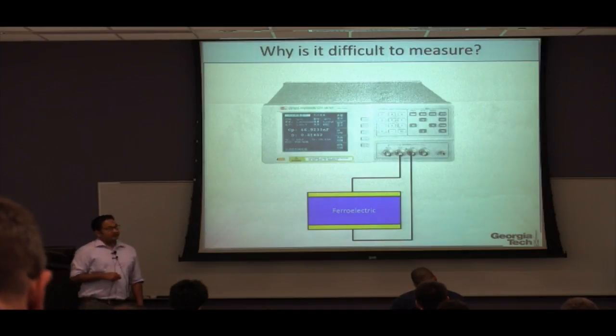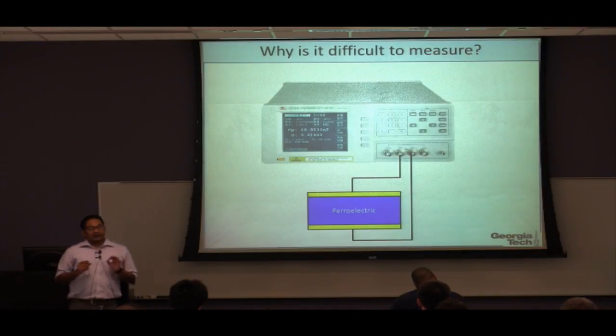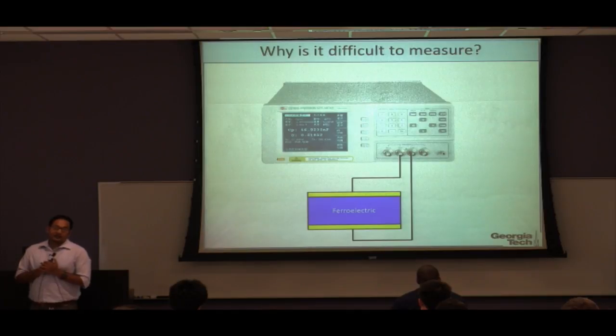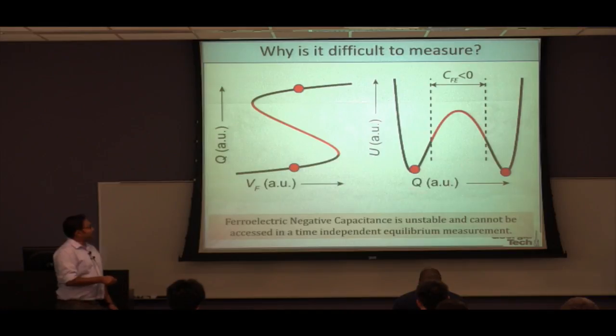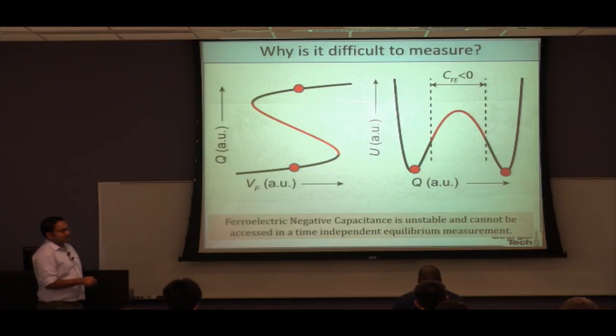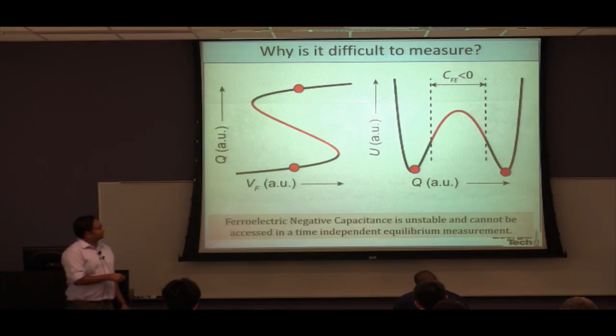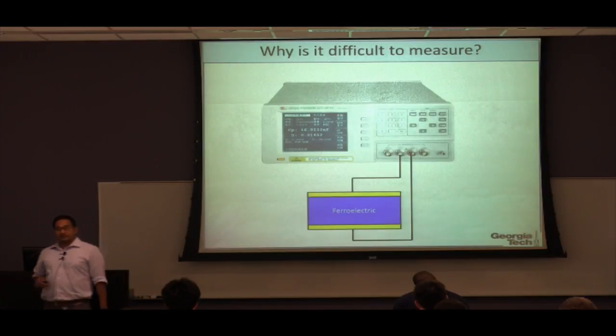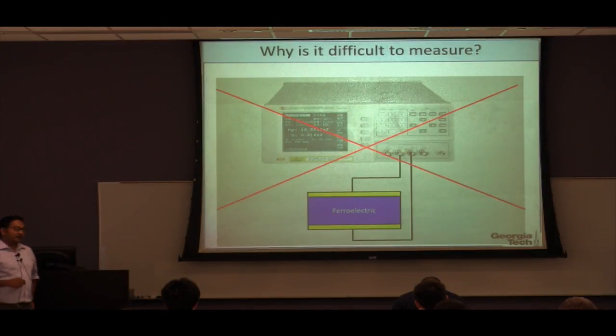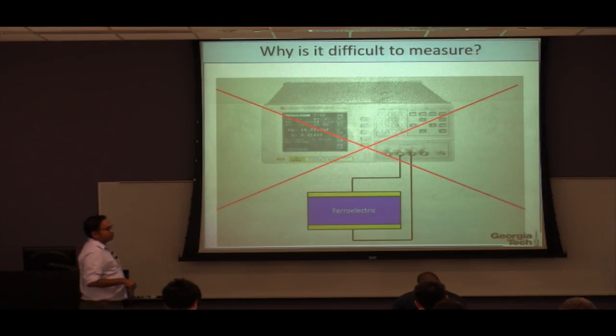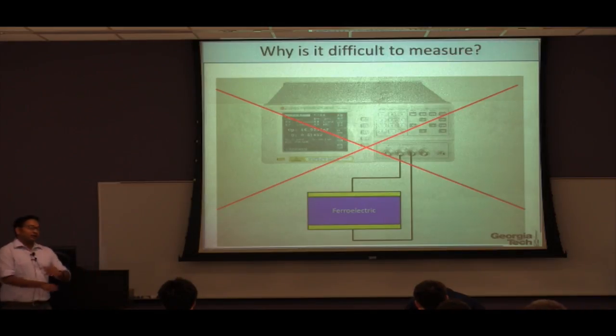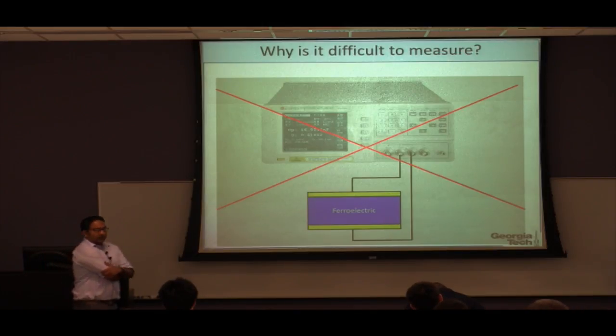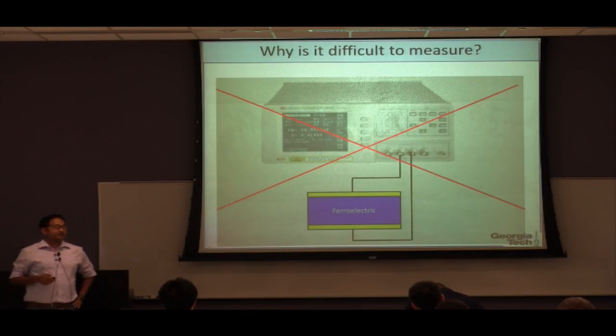This is why, if you take a ferroelectric material and connect it directly to an impedance analyzer, a capacitance meter, you won't be able to measure the negative capacitance, because what you will actually measure is the capacitance of these stable states. In these stable states, the radius of curvature is positive. As a result, you won't be able to measure negative capacitance directly by connecting a ferroelectric to an impedance analyzer, and this is the reason why negative capacitance was never measured until now. So we need a new type of measurement system to actually access this unstable negative capacitance state in a ferroelectric material.